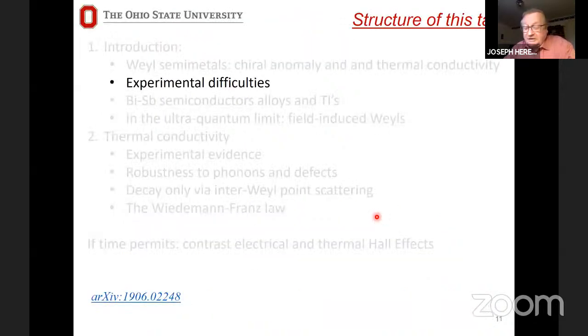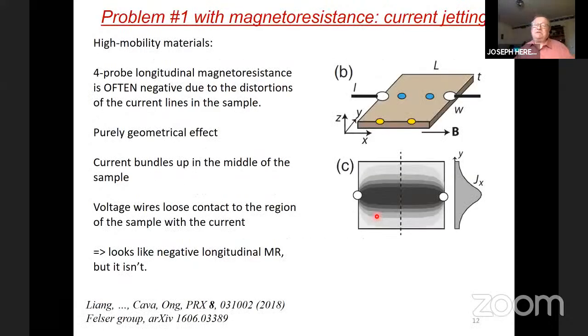Let me go a little bit over the difficulties with the experiments. And I will start with the problems in measurements of magnetoresistance. Weyl semimetals typically are materials that have very, very high mobilities. A million is not unusual. It's very easily obtained in these materials at low temperature.